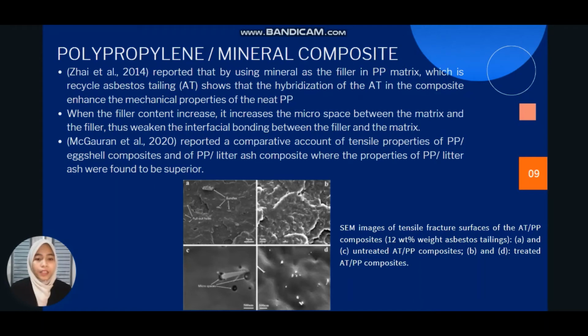So the figure shows the difference of tensile fracture, which is A and C show the tensile fracture for the untreated AT-PP composite, while B and D show the treated AT-PP composite. So in this case, it is shown that by adding mineral into the polypropylene matrix, it can enhance the mechanical properties of the polymer.